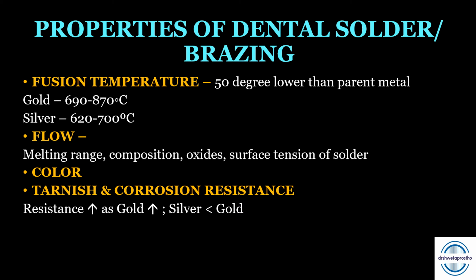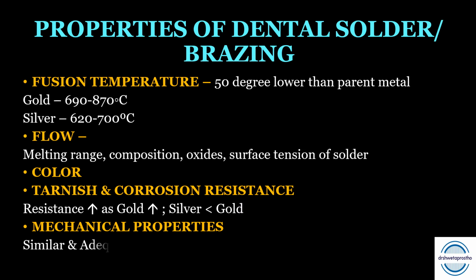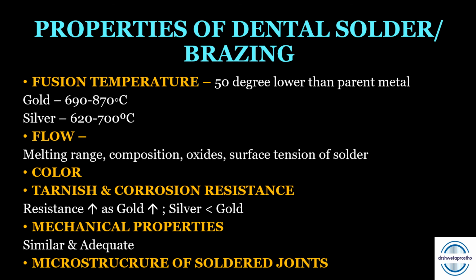Mechanical strength: the gold solders have adequate strength and hardness, and it is also comparable with the silver solders. Microstructure of the solder joint. On microscopic examination of the solder joint, the solder alloy should not combine excessively with the parent metal because it may lead to the formation of a third metal which has inferior properties.